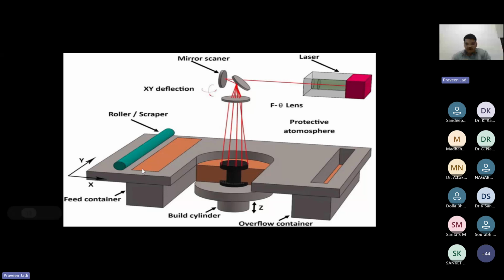Once we give the slice to the 3D printer, the recoater will come and spread one layer of coating. Coating means, suppose you are giving a 60 micron layer, it will spread a 60 micron layer. Suppose you are giving a 120 micron layer, it will spread the same amount of powder as that layer. Then the laser will come and scan the area where it has to deposit. Accordingly, the laser will sinter the powder. Then similarly, the recoater will spread the powder again, and the laser will come and sinter the remaining area. So layer by layer it will form the part.